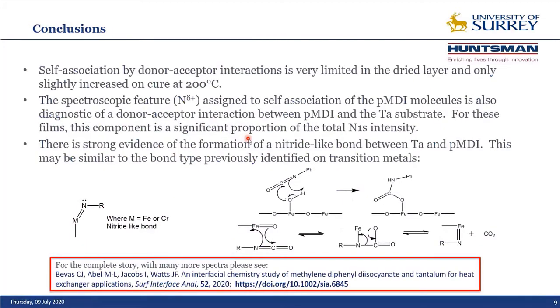So let's try and draw this together and see what we've learned in the last few minutes. Self-association by donor-acceptor interactions is very limited in the dried layer, and it's only slightly increased when we cure the thicker layer at 200 degrees C. This spectroscopic feature, this nitrogen delta plus, that is assigned to self-association of the PMDI molecule, is also diagnostic of a donor-acceptor interaction between the PMDI and the tantalum substrate. For the very thin films, this component is a significant proportion of the nitrogen 1s intensity, whereas for the thicker films, it's a very low proportion.